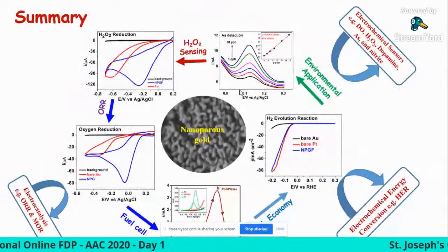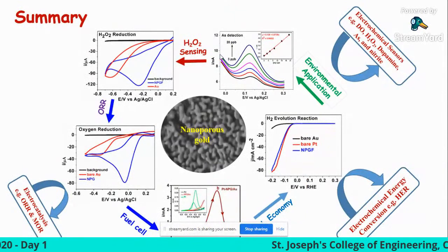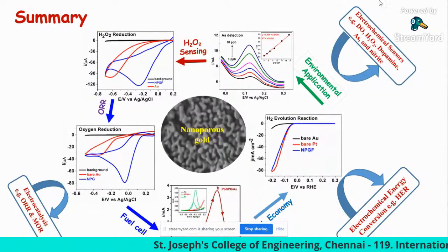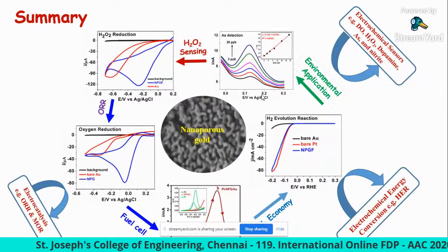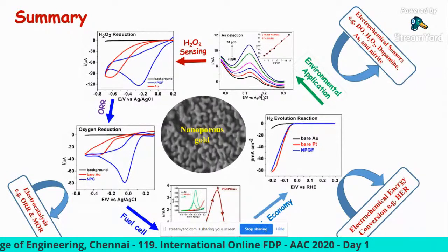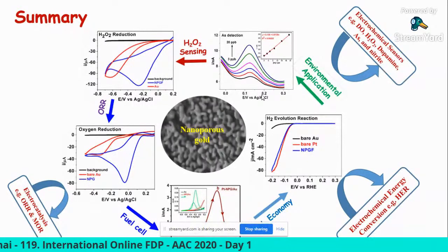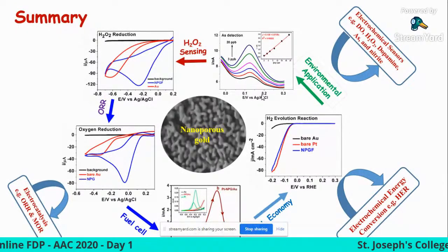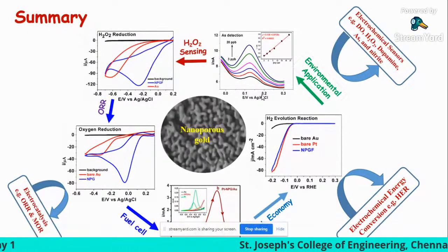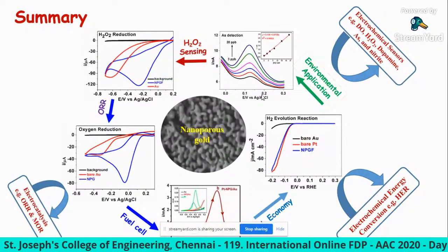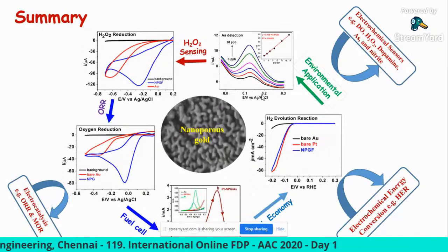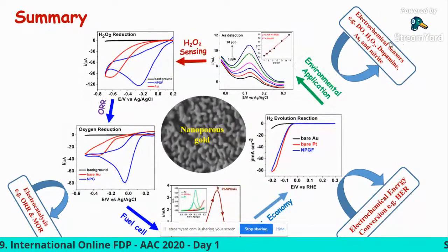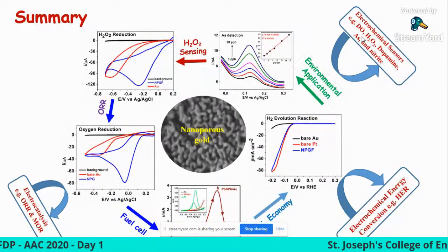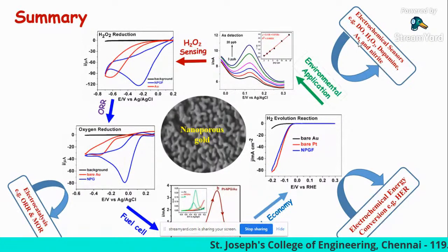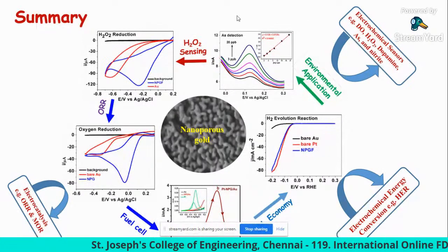So in summary, we have prepared the high surface area nanoporous gold in different ways. For example, the anodization electrochemical reduction method, the dynamic hydrogen bubble template method, or the anodization followed by chemical reduction method using dopamine as a reducing agent, and used it as an electrochemical sensor for dissolved oxygen, hydrogen peroxide, dopamine, arsenic, and nitrite.